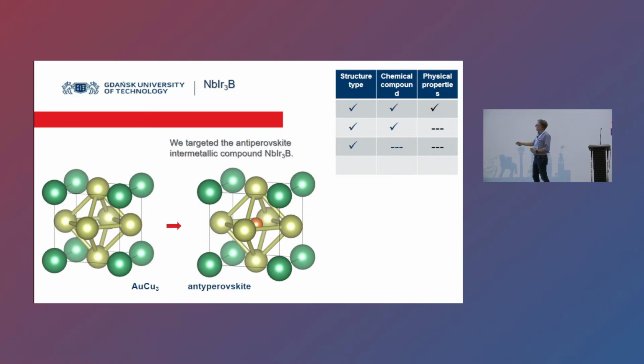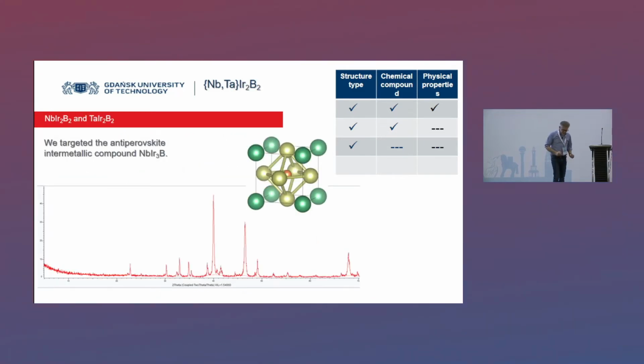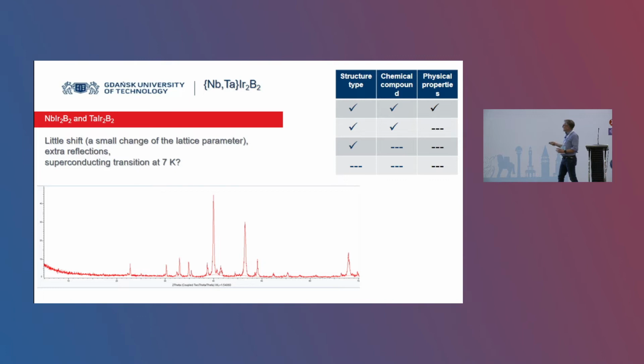And my former student melted several samples, and here is the X-ray diffraction pattern. So what you see here is the mess. There are a lot of reflections. Too many reflections to say that the sample is pure, of course. But nevertheless, we found that there is a main phase. The main phase is a cubic phase, which is shifted, fine, which is actually very good because the lattice parameter is larger. But there are extra reflections, and most important is the fact that there is a superconductivity at 7 Kelvin.